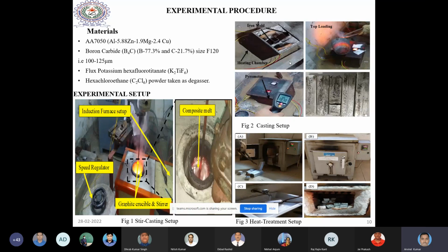Then for heat treatment, I have used this setup. So these test samples were made, and density was checked accordingly. This was the tribological setup which Sir has also shown. These are small components. The size was fixed at 6 diameter and 30 in length. I have used that pin, put it in the wear pin holder, and then we rotated it against a steel disc, EN31 disc. Against that, it was rotated, and we have seen the wear property.